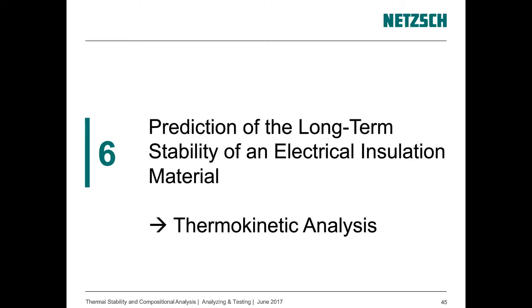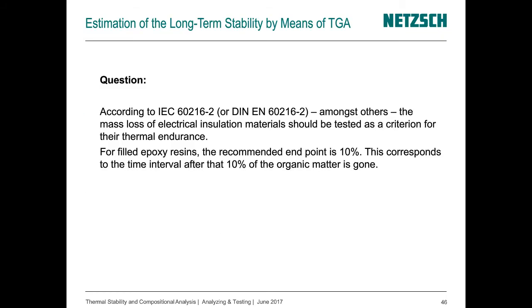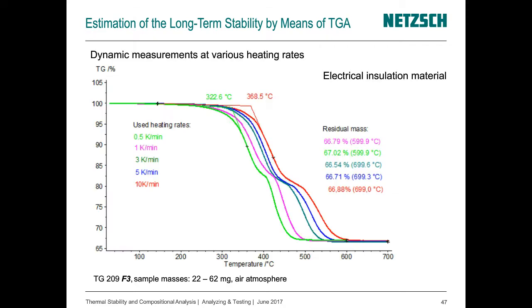And the task of this evaluation was to find a time interval after which 10% of the organic matter of an electrical insulation material was decomposed. For doing this, we made several measurements on this electrical insulation material, and you see here some of the dynamic measurements with various heating rates, from 0.5 Kelvin per minute, the light green curve, up to 10 Kelvin per minute, the red curve. What we see is a shift of the effects of the curves to higher values with increasing heating rate.